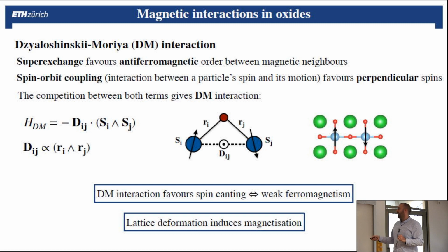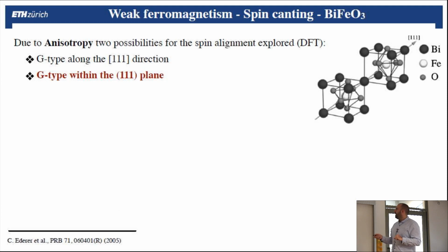And from that, you can see that when you have deformation in your lattice, it can also induce a magnetization. Because when you had the two spins in perfectly opposite directions, you have no net magnetization. But here, you have a net moment in the same direction, so it will result in a small magnetic moment of your system. So from this, let's go now back to bismuth ferrite.